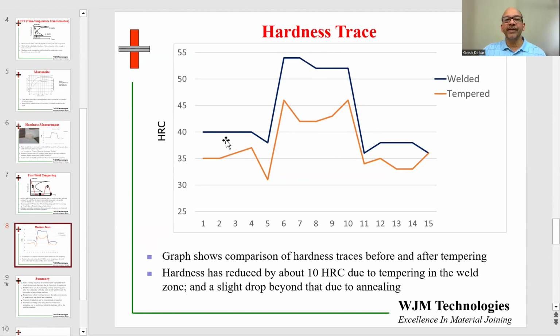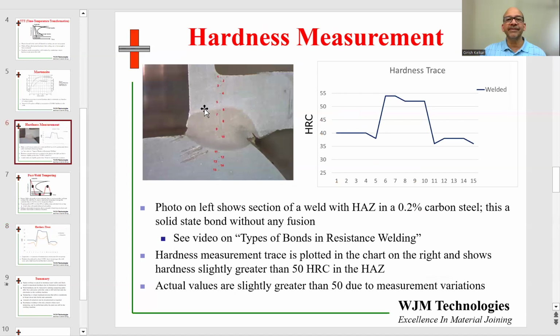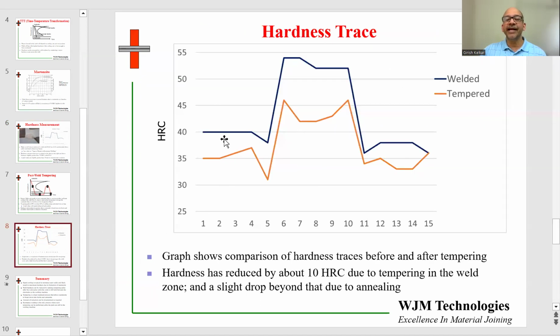You're also seeing a slight drop in hardness in the regions surrounding the heat-affected zone. So there is some amount of heating even beyond what is a visible heat-affected zone. So here it seems like this is the visible heat-affected zone, but there is going to be some heat dissipation further out. So the true heat-affected zone can be much further out, where there is a drop in hardness. Now, that drop in hardness on the edges is more from stress relieving. So whatever work hardening was there has been dissipated because this heat allows that part to soften. So the mechanism of softening further away from the weld is a little bit different, and the mechanism of softening where you see a more dramatic drop in hardness is because of the tempering cycle.